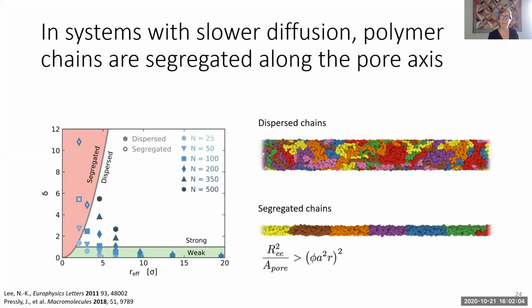because there's actually a phase separation or a segregation of the chains. So if you look at the lower right of the slide, when the cylinder is very small, the chains can no longer interpenetrate one another. They become these little plugs. And so this has also been seen, this is Lee's work from 2011, where this is a confinement parameter as a function of the radius of the pore. And I'll draw your attention to this curved line, which is separating the dispersed versus the segregated, right? And so the open symbols here indicate the simulations that had this sort of segregated chain morphology.